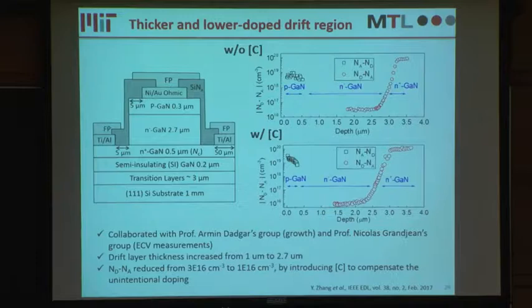After the leakage reduction, we also wanted to further increase the breakdown voltage. To do this, we need a thicker drift region. We collaborated with Professor Armin Dadgar's group in Germany, and they were able to increase this drift region from 1 micron to about 2.7 micron.